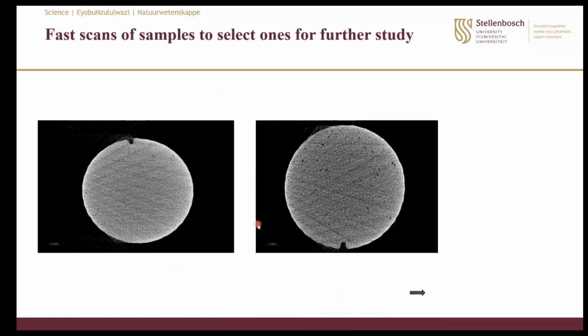And then for my individual research, because I'm looking at creating porosity intentionally so I can use different X-ray based systems for non-destructive testing, I printed 3 batches of aluminum samples that have some silicon and magnesium elements.